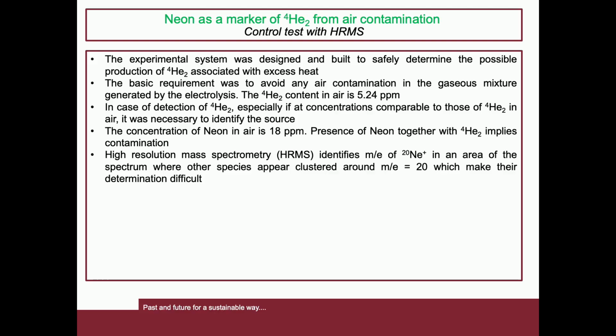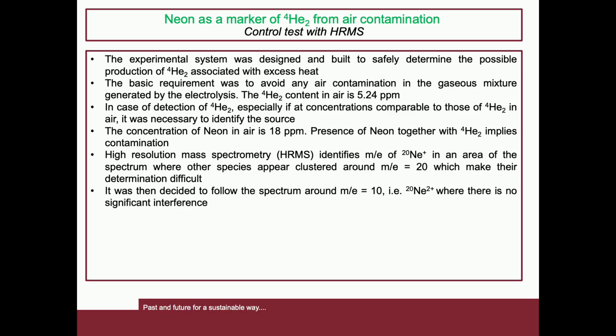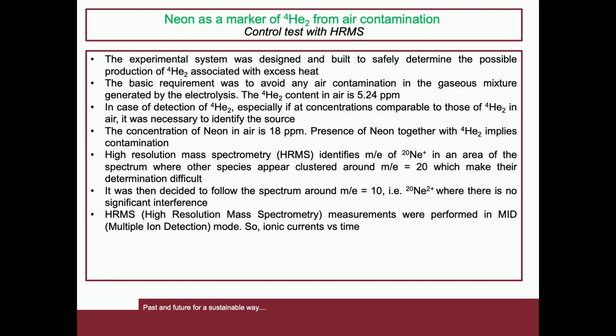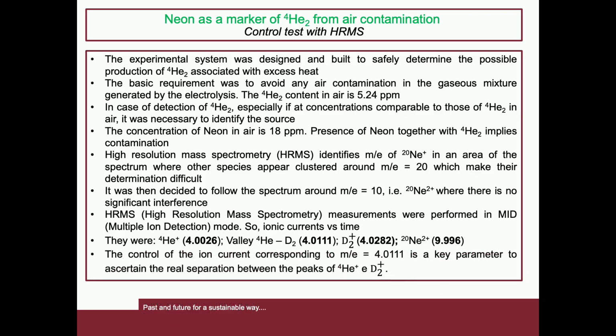The concentration of neon in air is 18 ppm. Presence of neon together with helium-4 implies contamination. Higher resolution mass spectrometry identifies a mass of neon-20 in an area of the spectrum where other species appear clustered around this mass, which makes their determination difficult. It was then decided to follow the spectrum around mass 10. It has neon-20 2+, where there is no significant interference.